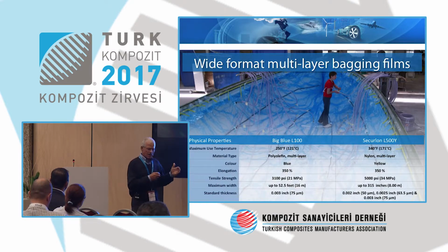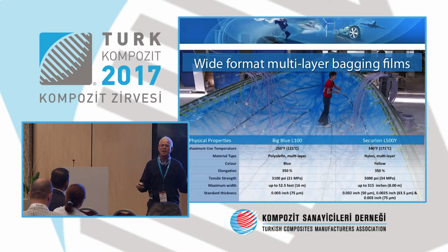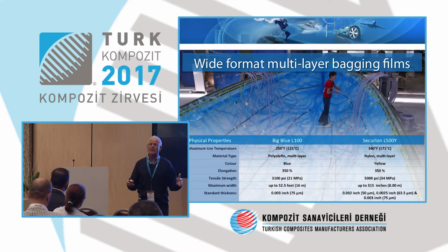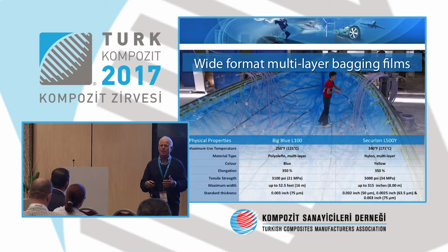So if you work in the desert, you obviously cannot work with nylon 6. So you have to go to a more stretch film. And if you work with a very chemical aggressive resin, your best idea is to go with a multi-layer film. A multi-layer film can be very strong, can be very high temperature resistant, and can also be chemical resistant. As an example, in the phenolic resins, you need a chemical resistant film, otherwise it just burns your bag and you lose your part, okay?